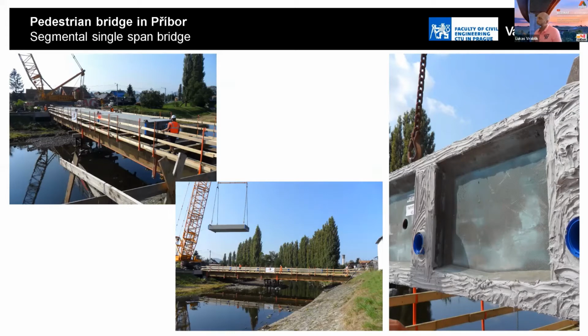It was done by a special steel element, you can see here the member. Every segment on the upper part and also on the bottom part has a special steel element. And these steel elements were connected by bars during the construction process, by prestressing bars. And by the prestressing of these bars, we could produce the compression in the joints for the glue, for the initiation process of the increasing of the strength of the glue.